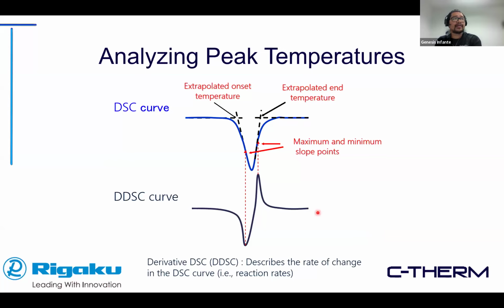Another feature typically associated with DSC, and again, this is typically added into the software itself, would be the derivative of the DSC curve itself. So you can see this is the original DSC curve, and the derivative of that looks something like this. What this derivative really describes is the change in the slope of the curve, effectively describing the rate of change of the heat flux during the event, right? So for example, right here, you can see that the slope is minimum at this point right here, and maximum at about right here. So we can extrapolate or get the rate of reactions, for example, from those data.